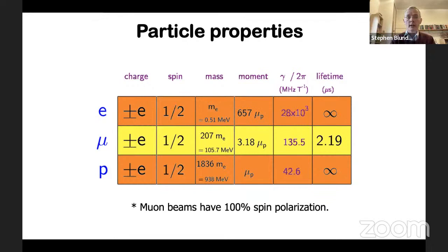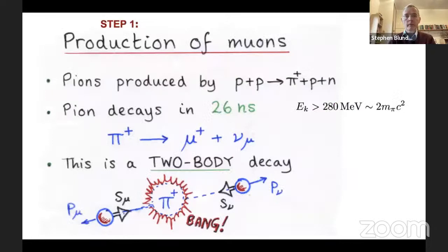And the other thing, if you compare the muon technique with the neutron technique, one great advantage we have is that you can put muons in anything. You don't have to worry, as you do with neutron scattering, that you have to make sure your samples are deuterated if they have hydrogen in. You don't have to worry about tricky elements like indium or cadmium that become very easily activated by the neutron beam. The muon beam will not activate them. So you can study any compound you like. There's no restriction. Okay, so let me just quickly go through how we do the experiment.